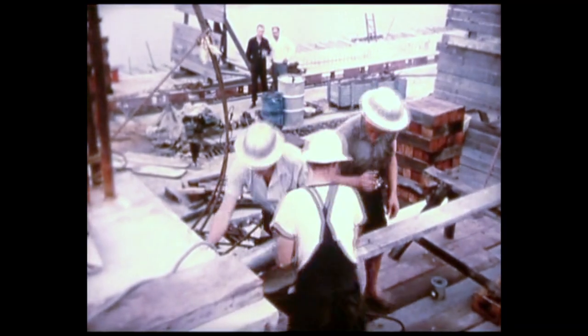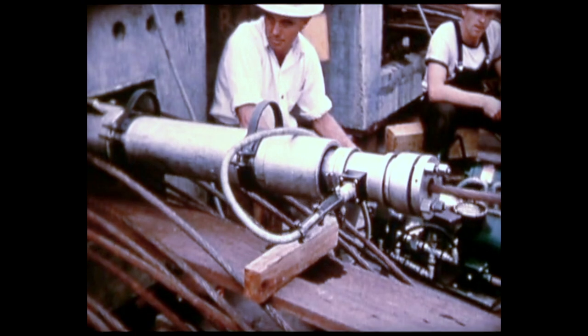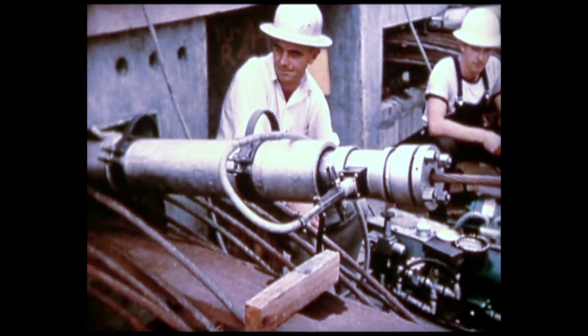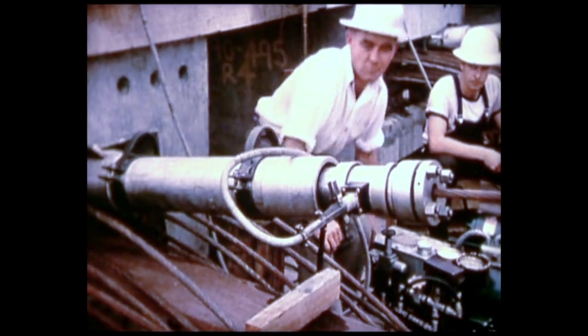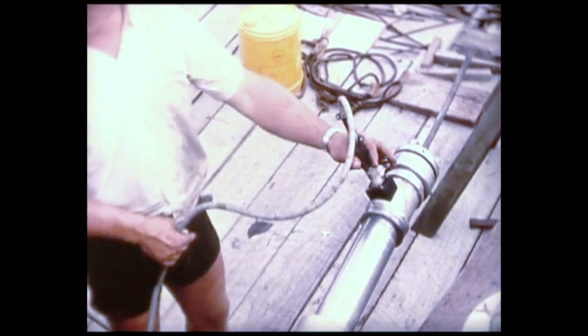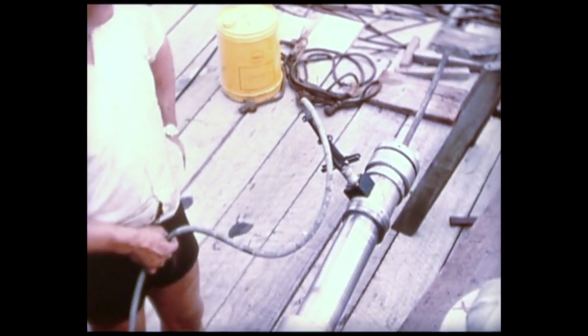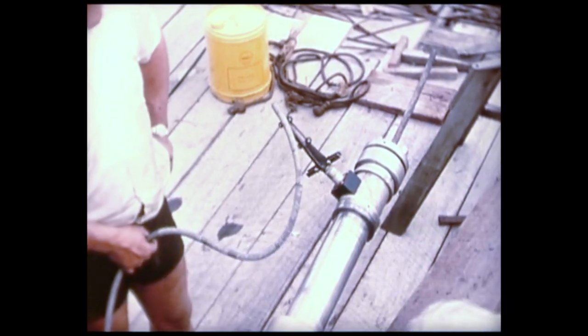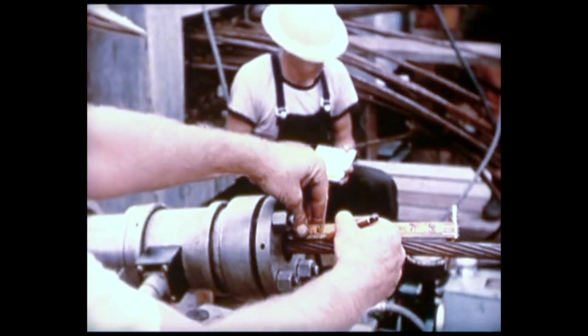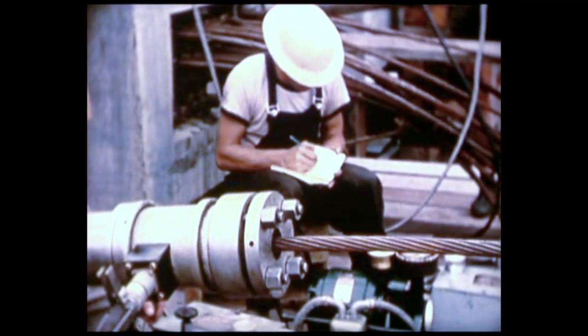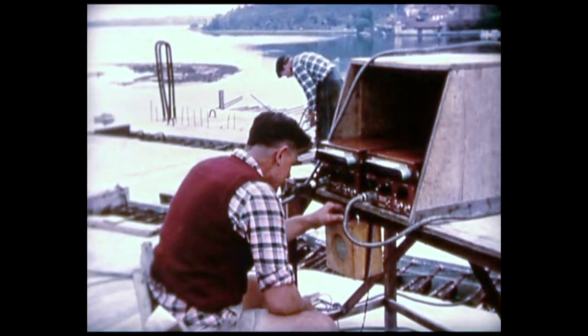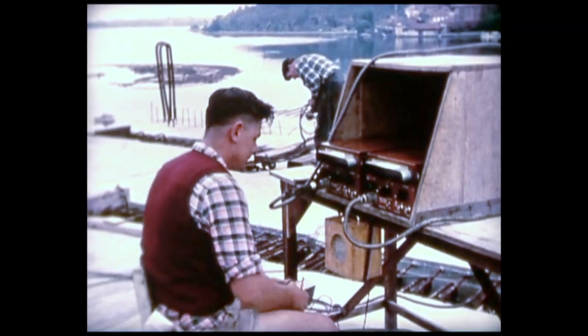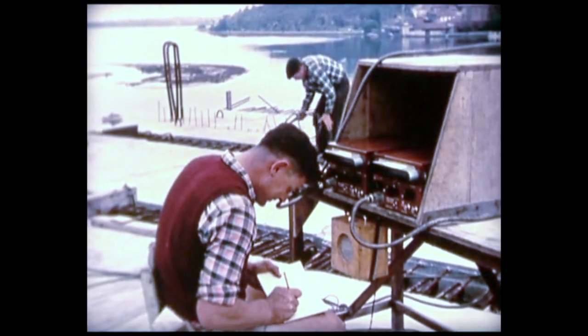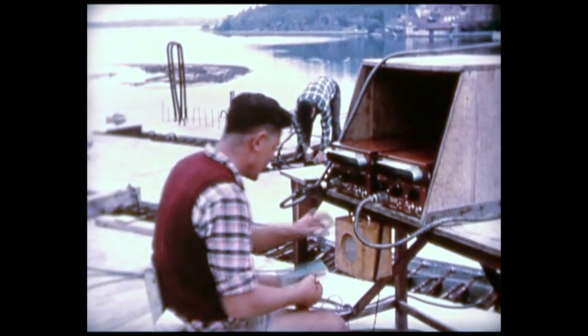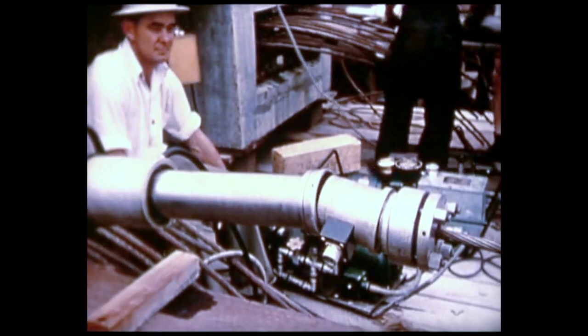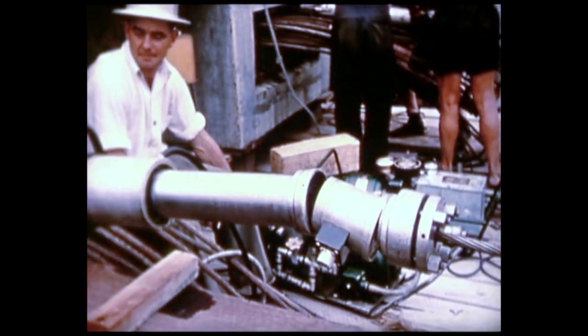The pre-stressing forces were accurately measured with load cells, the readings being taken on mirror galvanometers. The initial stress in the wires was 83 tons, and the final stress 63 tons per square inch. This is equivalent to 20 tons per rope. Although load cells were used for the final reading, a check on the load was made by measuring the extension of the cable. After tensioning, the cables were surrounded by concrete as protection against corrosion. In addition, the concrete and bolts through the web bonded the cables to the beams. Cable by cable, the stressing continued until all the ends were firmly wedged to anchor blocks.